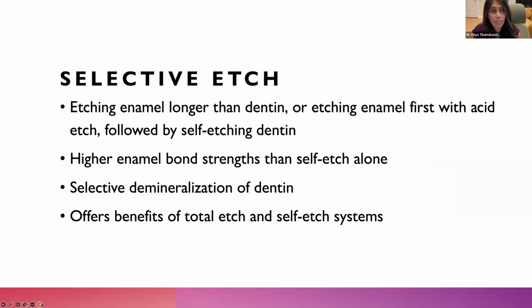And then moving on to selective etch. So selective etch refers to etching the enamel first with acid etch, followed by a self-etching dentin, or etching the enamel a little longer than the dentin. But there are higher enamel bond strengths than self-etch alone, and we can selectively demineralize that dentin. And so this method offers the benefits of both systems, both the total etch and the self-etch system, and is my preferred method.